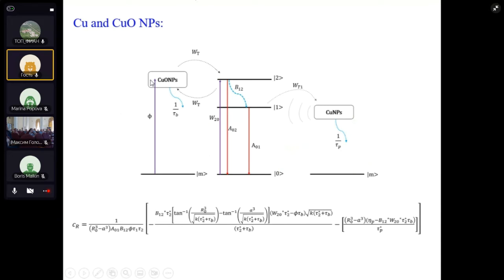And so in the case of copper oxide nanoparticles, no plasmon band is present. And indeed, what is playing a role is the interband transition in the copper oxide. And in this case, the lifetime is not as short as in the case of pure metallic nanoparticles. So you may have energy transfer from the copper oxide nanoparticles to more excited levels of the europium ion. And also, it's important to take into account a back energy transfer. Okay, the non-radiative decay rates, again, are very important.